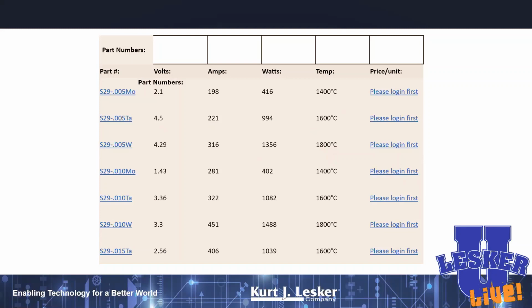Now, after I do one deposition or so and my boat cracks and I'm all upset about that, you call the Lesker company and the person on the phone is going to say, hey, use a thicker boat. So go for a 10/1000th of an inch thick tungsten boat. But notice now the requirements for your power supply have changed. So now it's 3.3 volts. It's 451 amps in order to get you that same 1800 C. So just be really mindful about what your power supply can do. That will completely dictate the suite of materials you can do by thermal evaporation.